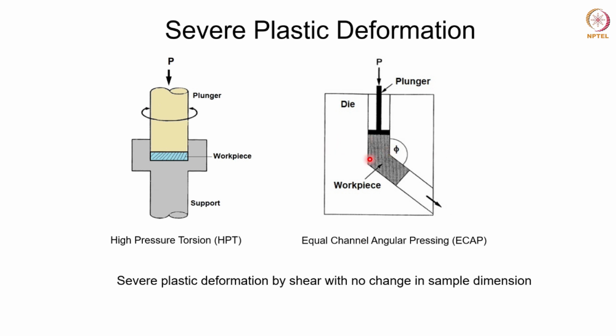Similarly, there is a process called equal channel angular pressing, or ECAP in short, that also leads to a very large strain into the material and deforms it severely, leading to grain refinement. All these things are done on a solid billet. As you could see, it can be in different size and shape depending on the die geometry. So here, for example, in the case of ECAP or even this high pressure torsion, you can use a cylindrical shape workpiece in the beginning, and then you can deform it in a die, leading to severe plastic deformation and grain refinement.